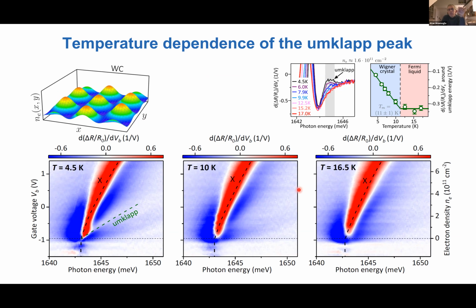So the short answer is no, because I'm looking at the exciton branch, or the repulsive polaron branch. This is basically the modification of the free exciton due to its interaction with the lattice. You can also ask this question: if I directly excite the attractive polaron branch, what I'm doing is a collective excitation of many trions. And in that case, I should also be able to see the periodicity, but this will only happen if my electrons are spin polarized. In principle, at high magnetic fields, we should be able to see this. I must say that we haven't looked at features at the attractive polaron. But in principle, yes, there is a regime, but it's not relevant for the experiments that we're discussing here.